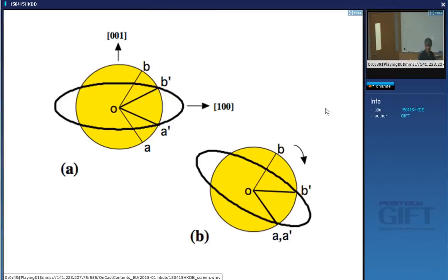interface. Okay. However, if to the Bain strain we add a rigid body rotation, then we can produce one invariant line, but the other one goes out of coincidence by double the angle. Yeah? So with a rigid body rotation and a Bain strain, you can get an invariant line strain, so that satisfies the condition for martensitic transformation, and that extra rigid body rotation exactly predicts the observed orientation relationship. Okay. So the Bain orientation is of course not what we observe, but if we add the rigid body rotation that produces this coherent line, then that exactly predicts the orientation.